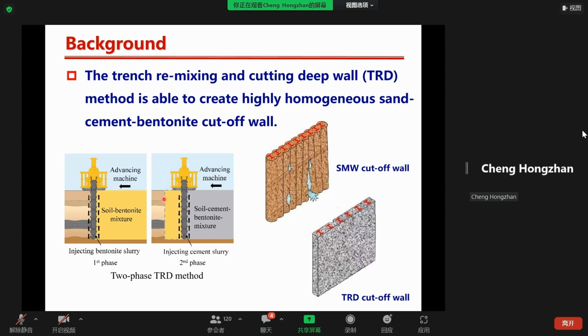In the left figure, it's the two-phase TRD method. For the two-phase method, as shown in the figure, the natural soil is first cut and mixed with the cutting fluid in the first phase, and the sand bentonite mixture is remixed with the hydraulic binder in the second phase. Bentonite slurry is typically selected as the cutting fluid, and the cement slurry is usually selected as the hydraulic binder. For the one-phase method, the natural soil is cut and mixed with the two slurries simultaneously.